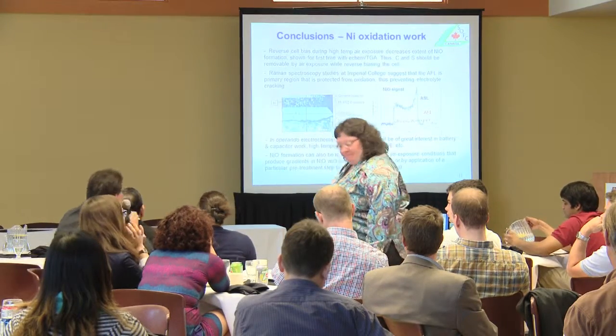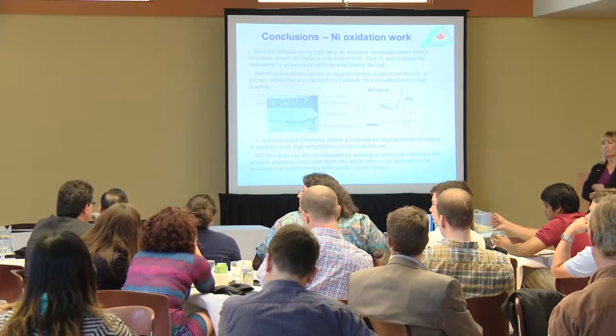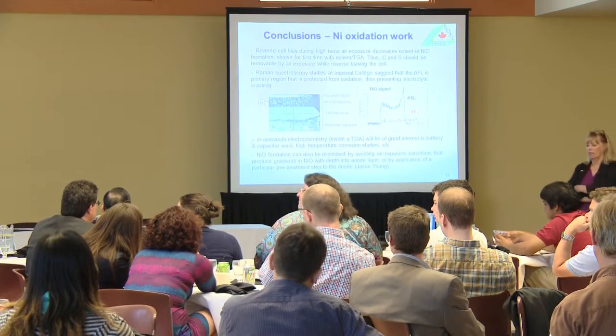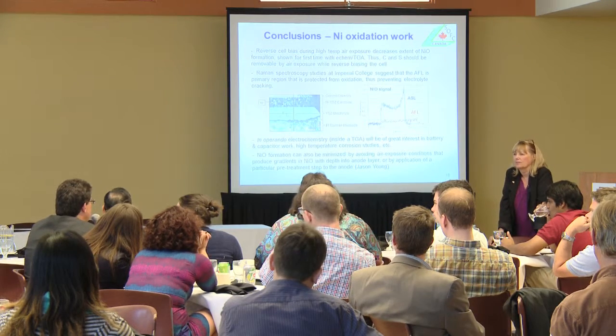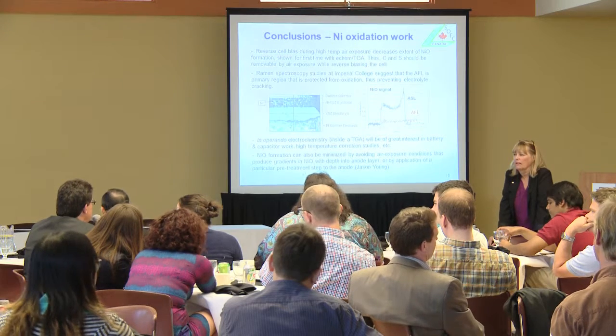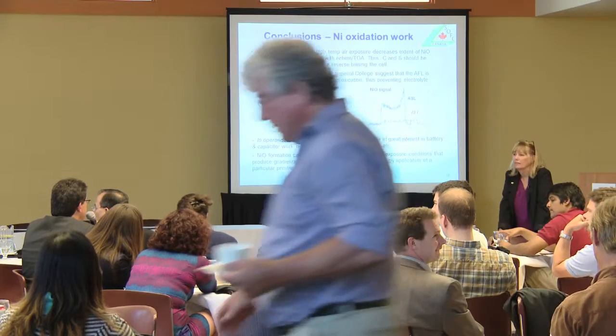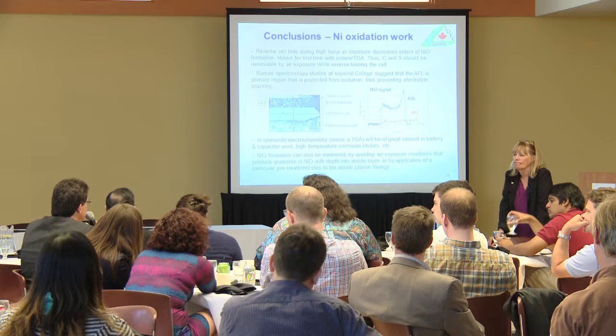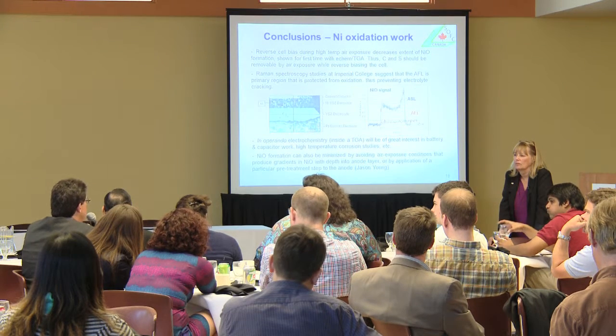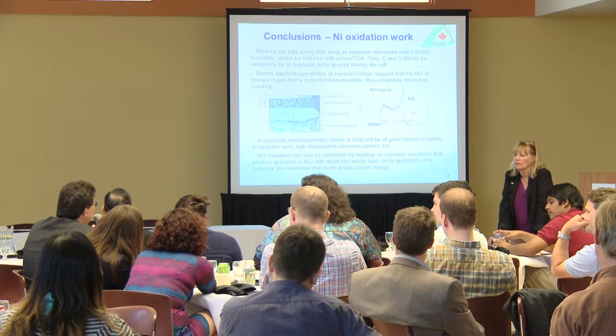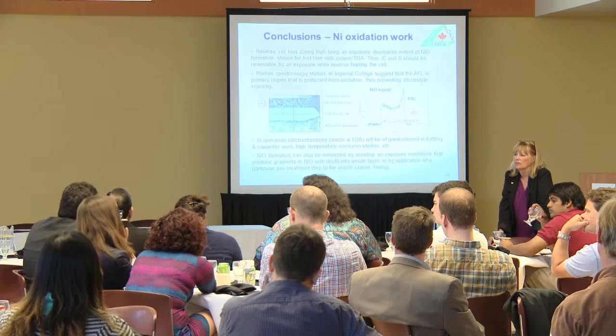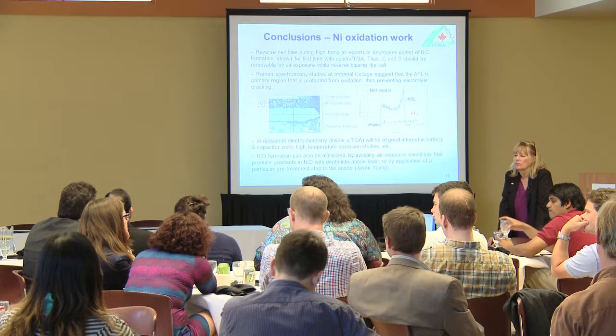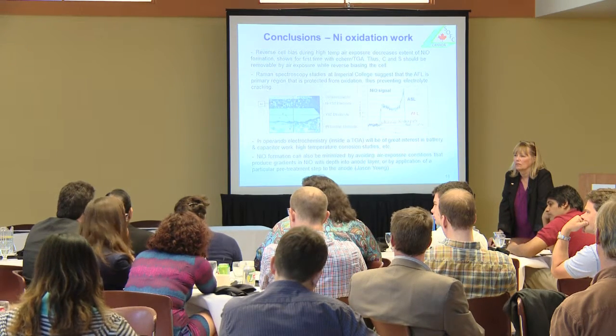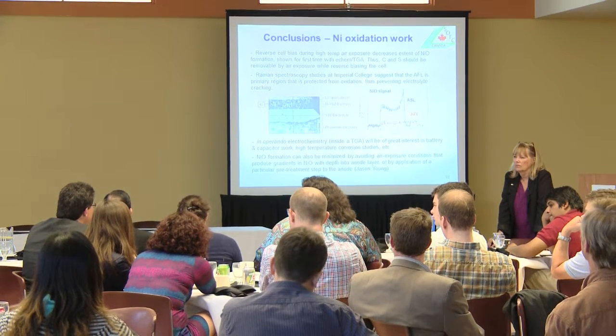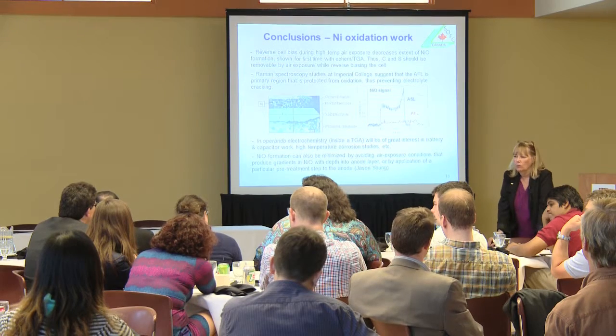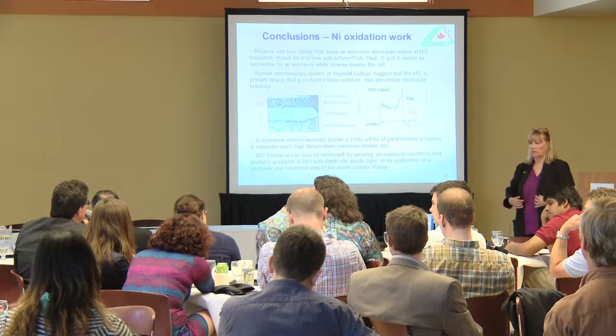Thank you. Very interesting results, Viola. It is well known in the literature, and it is even applied in the industrial reforming, to partially poison nickel with sulfur to avoid carbon formation. And this is attributed to the fact that when we have partially poisoned nickel, the size of the grains of the nickel decreases, and this is considered as the cause of the less carbon formation. But given what you have produced, that the sulfided nickel facilitates the oxidation of the molecules at the surface, is it possible that this effect is due to the more labile oxygen movement at the surface of this species, instead of having decreased the carbon formation rate?